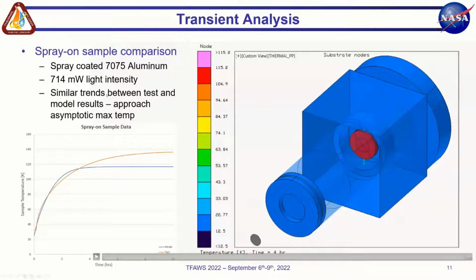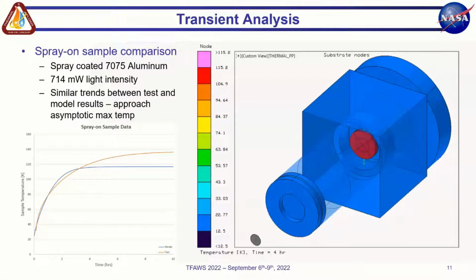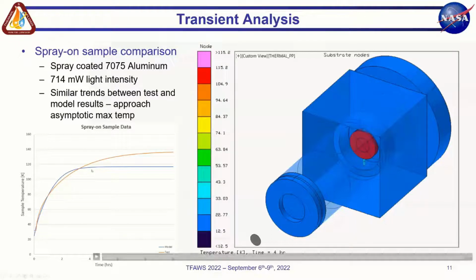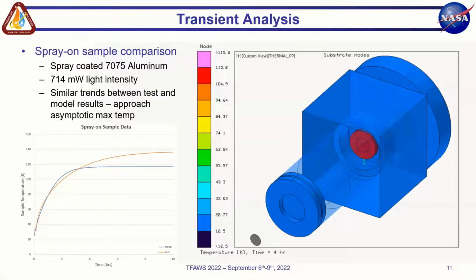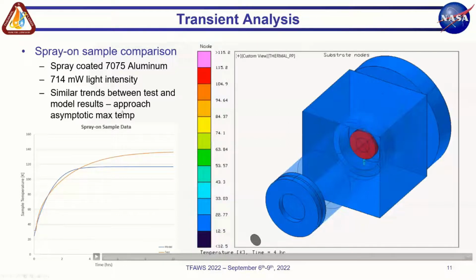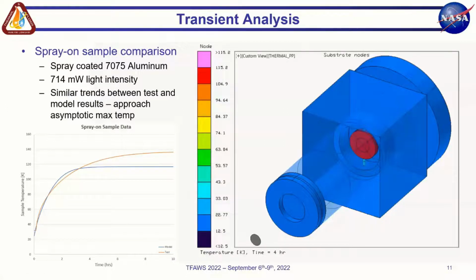So this is looking at a spray-on sample case where we spray coated a 7075 aluminum disc. And you'll see that the trends are not exactly a match, but they are similar between the test and the model results. So that's what we wanted to see. And that could be because of slight differences in the specific heat data or some other discrepancy that we had. But they both approach an asymptotic maximum temperature, which is a good sign.